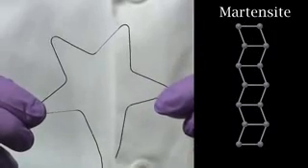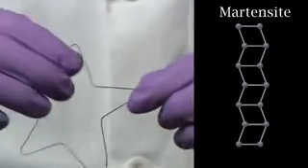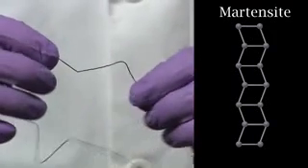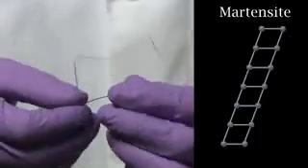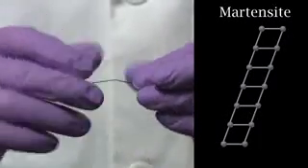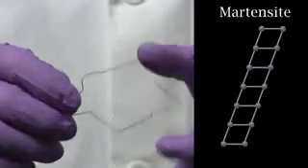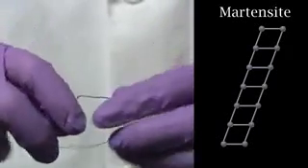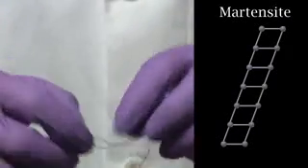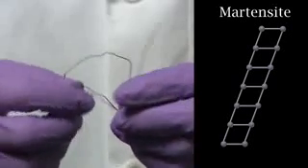In the graphic, you can see that the atoms have the martensite structure, but they align in a zigzag pattern so that the overall shape does not change. Now, we can bend the wire however we like. The material does not change phase, but the alignment pattern changes slightly so that they align in one direction. This results in a permanent shape change.